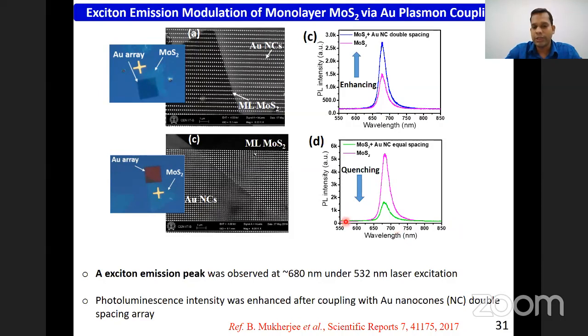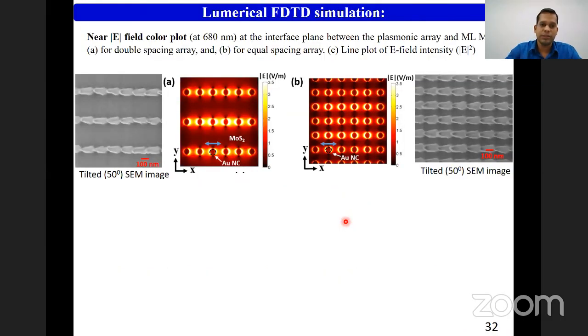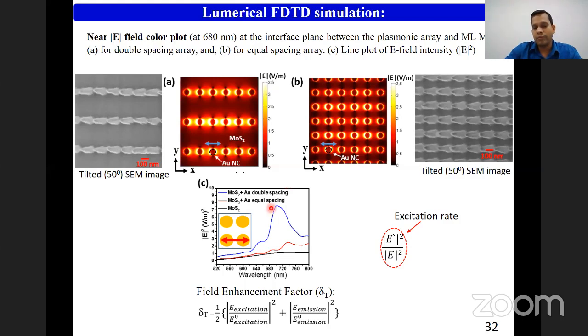So that is really very interesting, and we further characterize using simulation and a theoretical approach. We do the FDTD numerical simulation at the interface between the gold nanocone and the MoS2 surface. At the interface, it shows that the induced electric field, as shown here, gets enhanced. The line profile of induced electric field intensity is shown here, which shows that the electric field intensity gets enhanced in both the excitation wavelength and the emission wavelength for the double spacing array as compared to equal spacing.